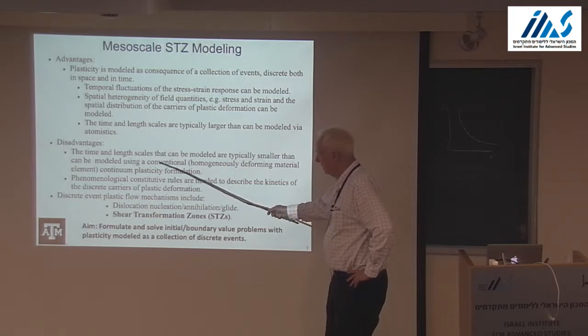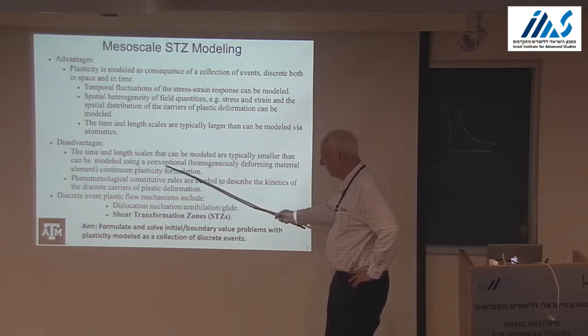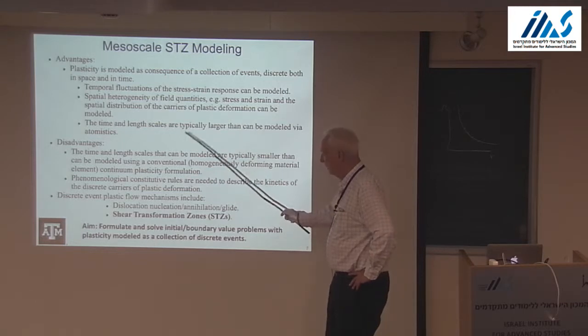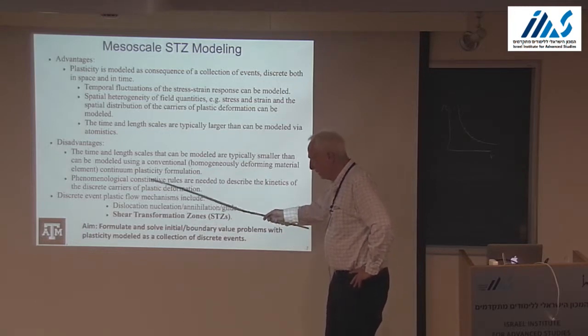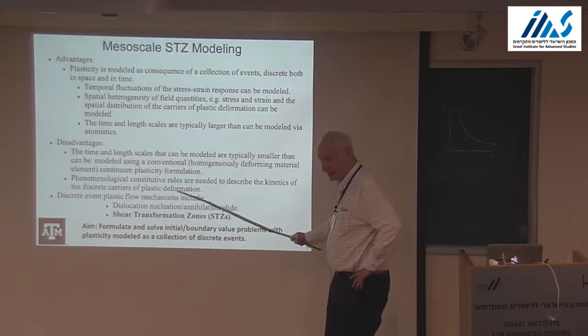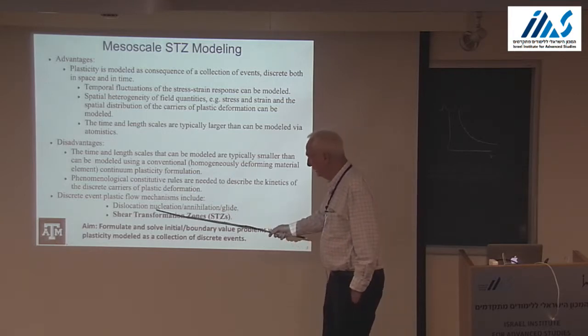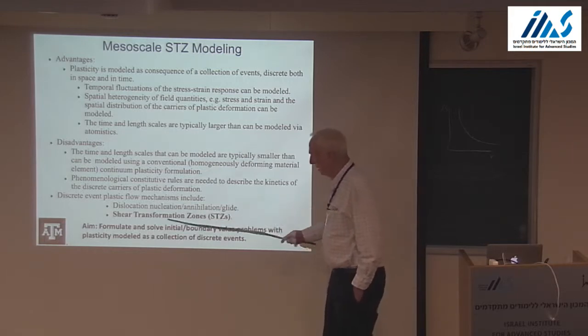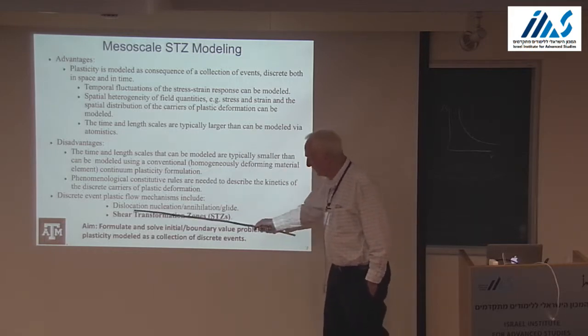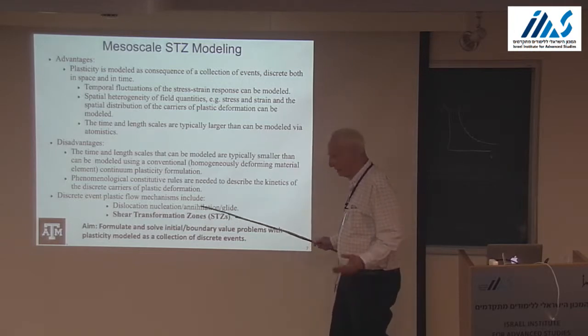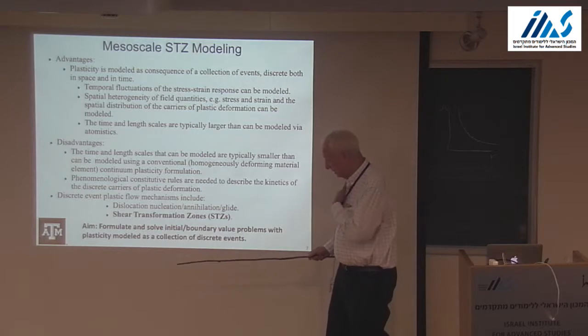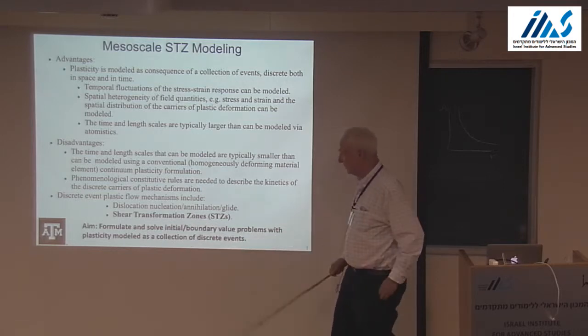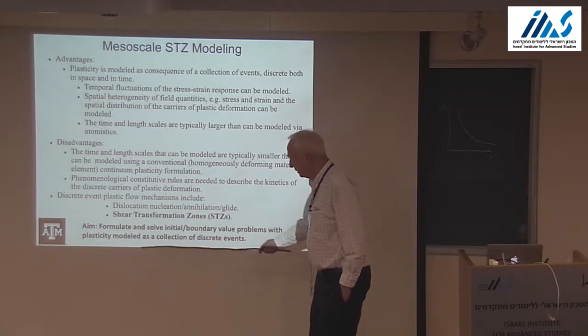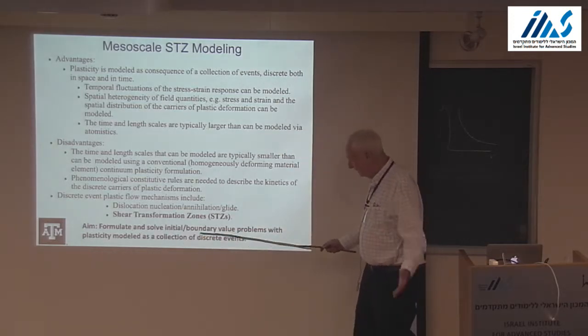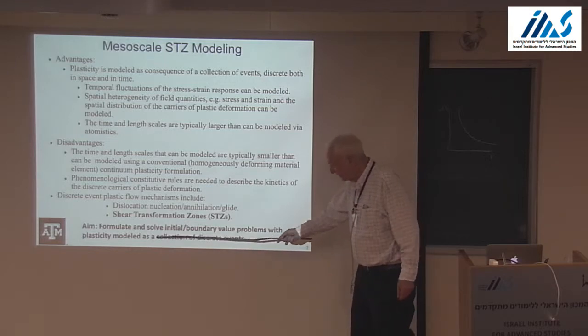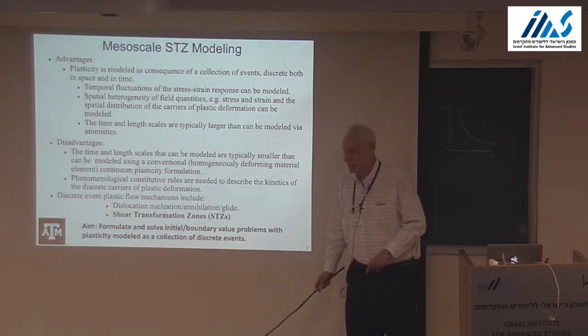Disadvantage: the length and time scales are typically smaller than can be modeled in a continuum framework. We need phenomenological rules to describe the kinetics of this transformation. Examples of such mesoscale events are dislocation nucleation, annihilation, and glide, discrete dislocation plasticity, and these shear transformation zones that I'm going to talk about. So our aim is to formulate and solve initial and boundary value problems with plasticity modeled as a collection of discrete events.